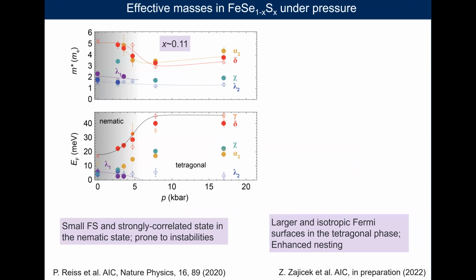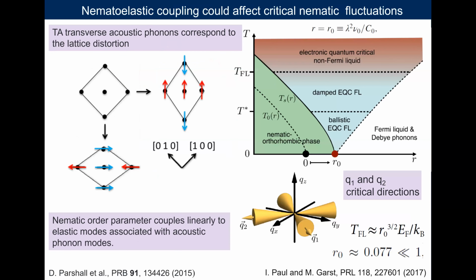And to summarize, the trends under pressure, which are also the trends with chemical pressure: inside the nematic phase, we have heavy masses, and it's a strongly correlated material with low Fermi energy. But as we move away from the nematic phase into the tetragonal phase, the Fermi surfaces expand and the masses change only slightly outside the nematic phase.